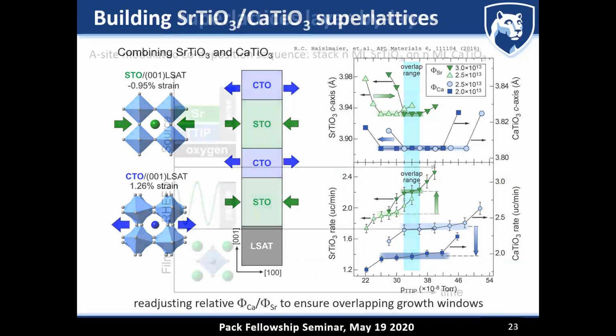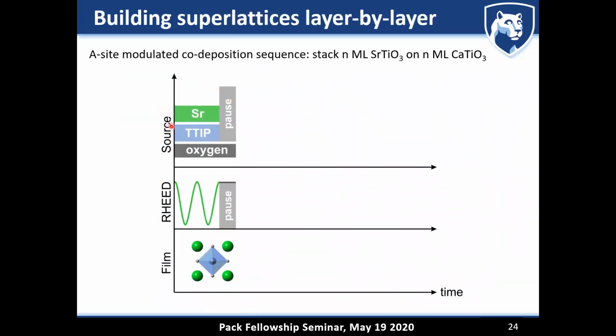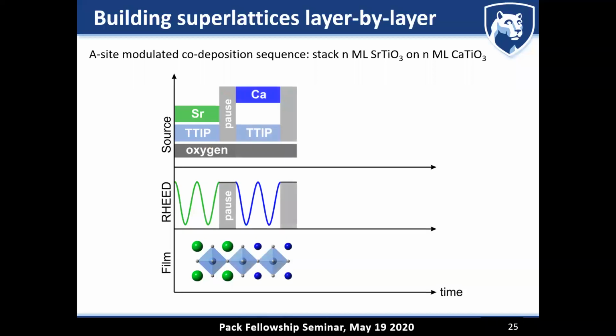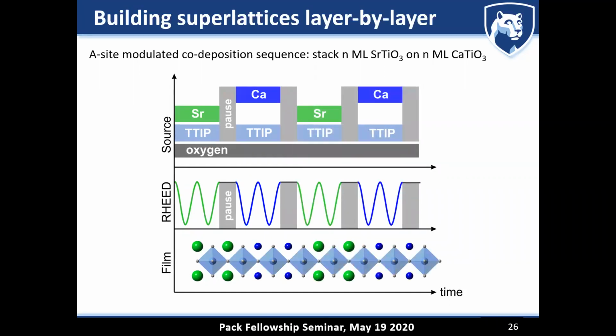superlattice stack. And so the idea of what we were really trying to do is an A-site modulated co-deposition of the superlattice stack, where you supply strontium and this titanium-containing metal organic precursor for some time, you know, a monolayer or 2 or 5. Then you pause to give the adsorbates on the surface some time to diffuse into the right position. And then you switch over and co-supply calcium and TTIP. You pause again, you switch back to strontium titanate, pause, switch back to calcium titanate. So in principle, we would expect, from RHEED oscillations, to see layer-by-layer growth, always n monolayers of strontium titanate and then n monolayers of calcium titanate. And ultimately, you should end up with a stack that looks like this.